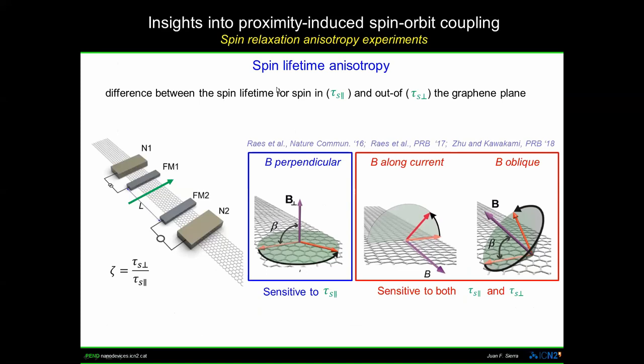The idea is how we can gain insights into this proximity-induced spin-orbit coupling and the spin texture. What we measure is the spin lifetime anisotropy — the difference between spin lifetimes when the spins are precessing in-plane versus out of plane. Depending on how the spins precess, you measure this ratio, which gives an indication of anisotropic behavior. Applying the magnetic field out of plane with spins injected in-plane causes them to precess in the graphene plane.